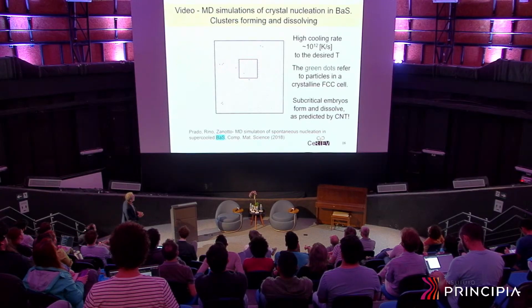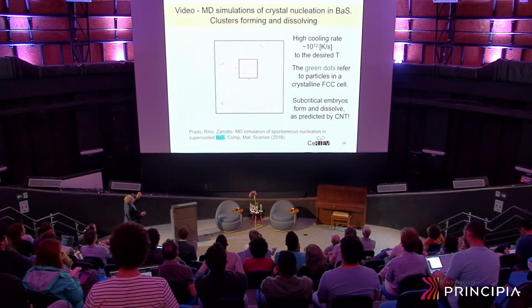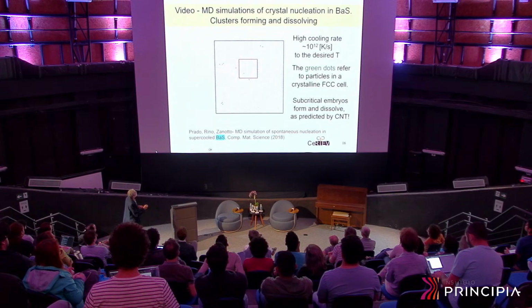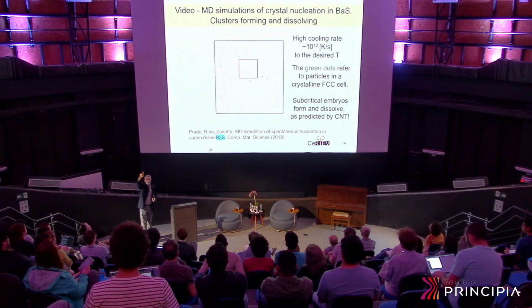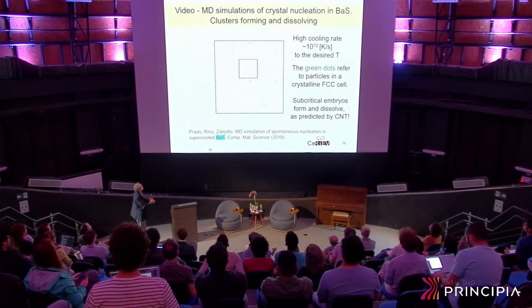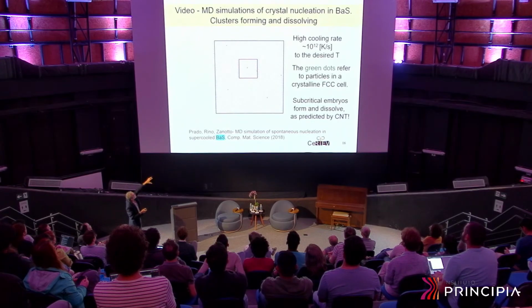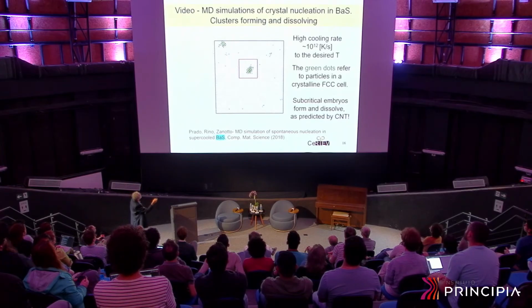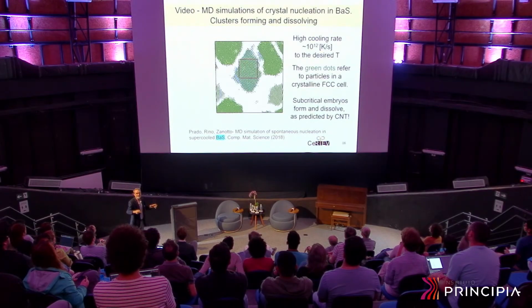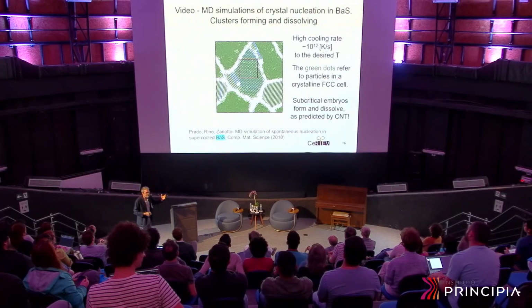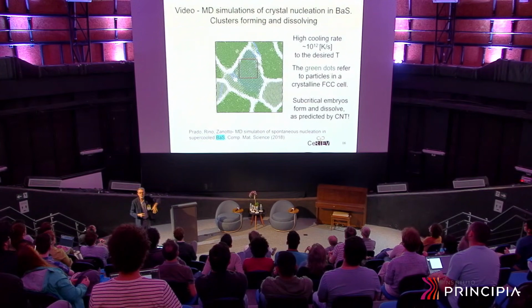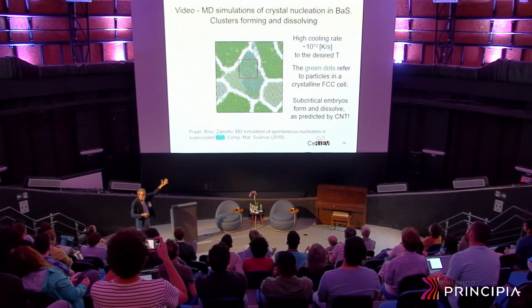Anyway, let's take a look at this. This is a real computer simulation, an MD simulation of barium sulfide at a certain temperature. Video, please. Fluctuations are forming and dissolving. The green dots are crystalline fluctuations. They're forming, dissolving, forming, dissolving, until a critical size is reached, and then they start to grow. So these simulations confirm Gibbs' ideas on the fluctuations forming and dissolving. This is the process of nucleation.